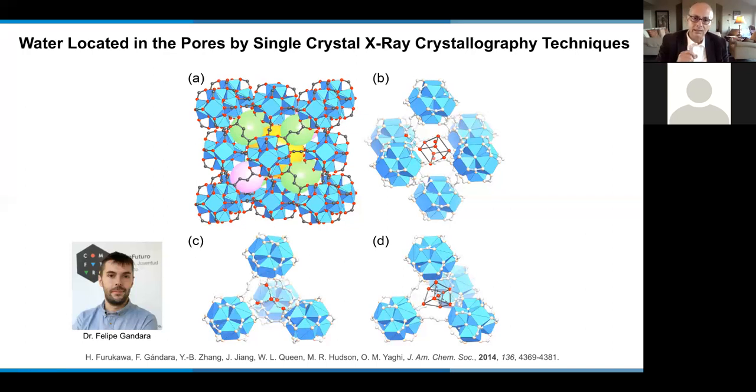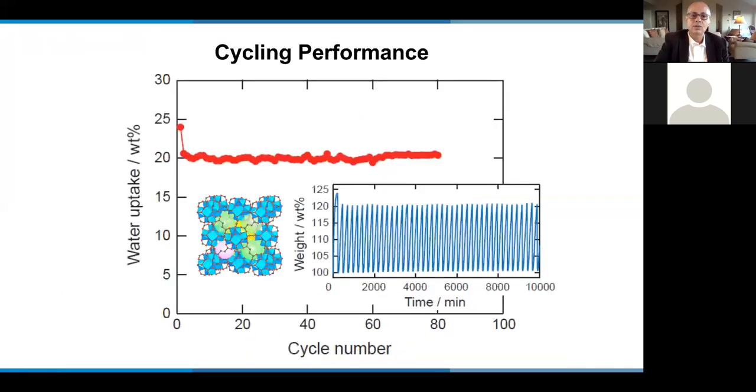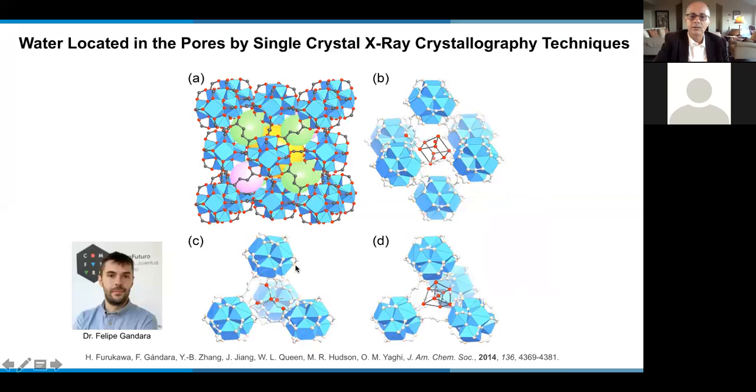And so we immediately realized that, in fact, that drop that we saw here must be these water molecules that are strongly bound to the hydrophilic metal oxide unit. And indeed, it's those water molecules onto which further water molecules bind and build up in the pore, as if you were building up a piece of ice inside the structure. It was absolutely fascinating. And now you can see why many MOFs could be used for water harvesting from air, because the most hydrophilic centers are going to be where water binds and stays. And in a way, protecting the framework from any degradation over a period of 4 or 5 years, which is exactly the amount of time that these materials would be graded for in a device.